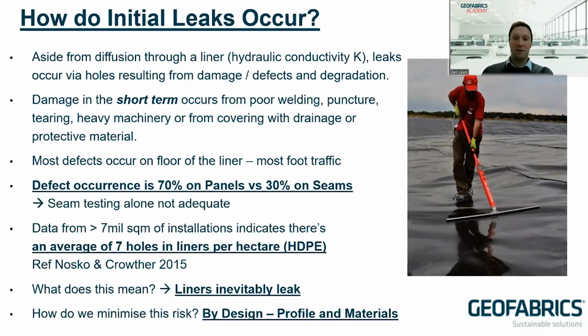And that's important because depending on the job, you might only find that it's a requirement to test the seams, which is easy enough, but it's a little bit more challenging if you don't have the right preparation and materials to test the panels. But we should be testing panels because that's primarily where your leaks are going to occur. But it just does tell you that seam testing alone really isn't adequate anymore. There was a good paper here, which I've referenced here, where they looked at over 7 million square meters of HDPE installations, and they found an average of 7 holes per hectare. And that's quite a lot. It's probably gone up over the years, I think, probably due to the better testing methods. But it's another reason that we should be testing our liners before we're commissioning them.